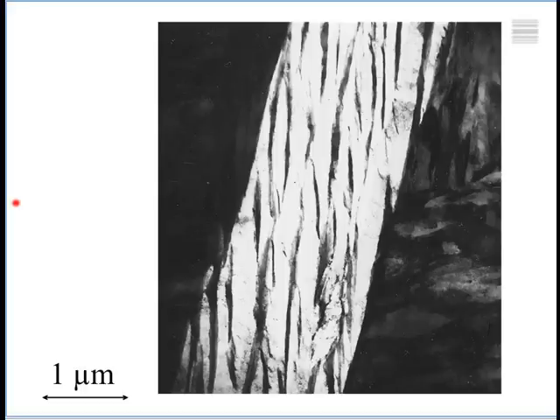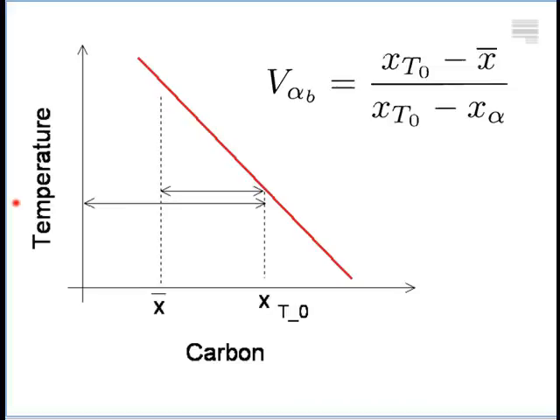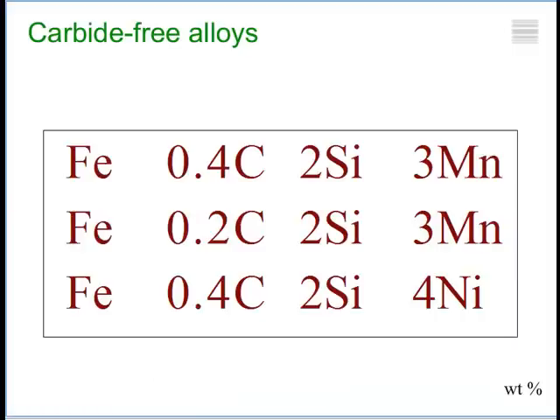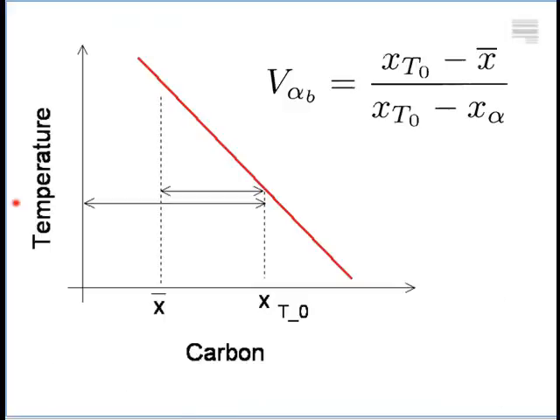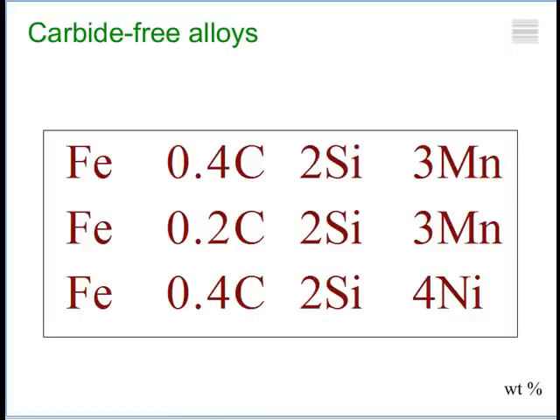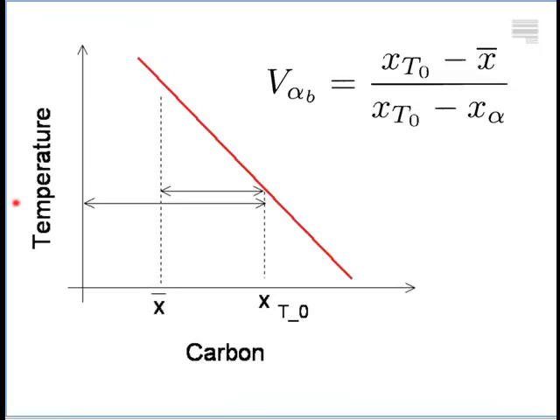So let's imagine that by calculation, we work out the T0 curve and we design three steels. Okay, this is a 0.4 carbon steel, two silicon. Silicon is the same, it's to stop the cementite precipitation. Here we have three manganese. This is a 0.2 carbon, two silicon, three manganese. So all I've done here is I've reduced the average carbon concentration by a factor of 2. So that's this value. If I reduce this, then I can increase this. And this steel is the same as the first one, but manganese is replaced by nickel, and that has the effect of shifting the T0 curve to larger concentrations.